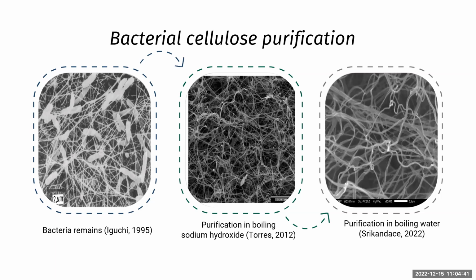But sometimes sodium hydroxide is also required during the purification, because studies proved that the addition of sodium hydroxide in a very low concentration was reported to increase the mechanical properties of the resulting gel.